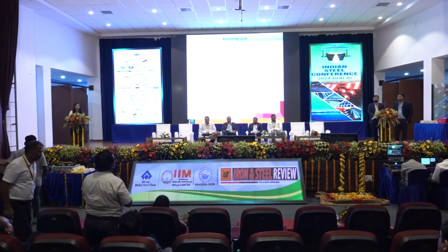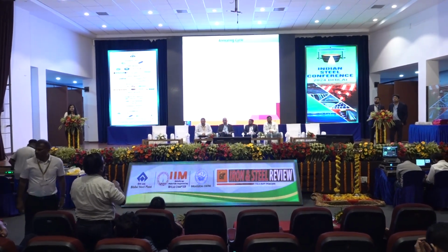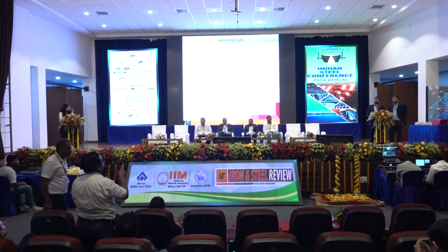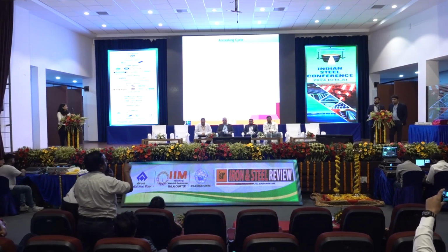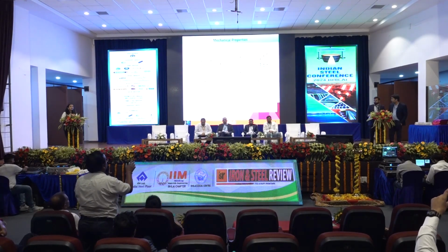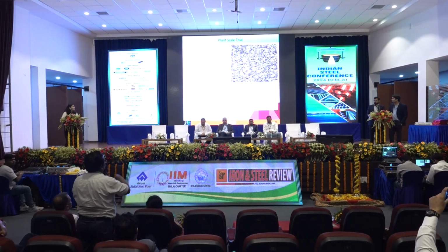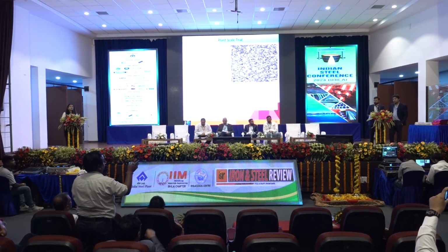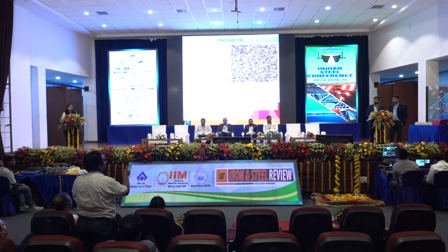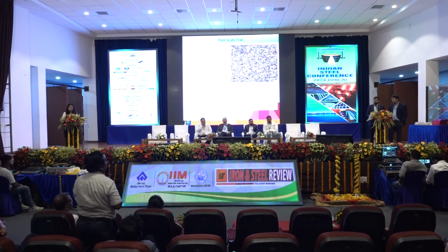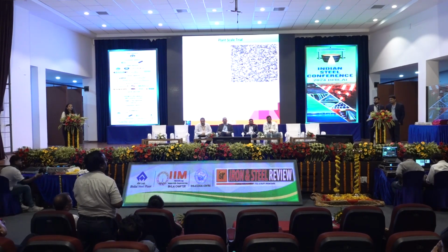Hello. So you have shown that single step, and then at 650 degrees Celsius you are giving here. So from ambient temperature to 650 degrees Celsius, there will be a temperature difference between the core and the surface. So there will be thermal stresses developing.